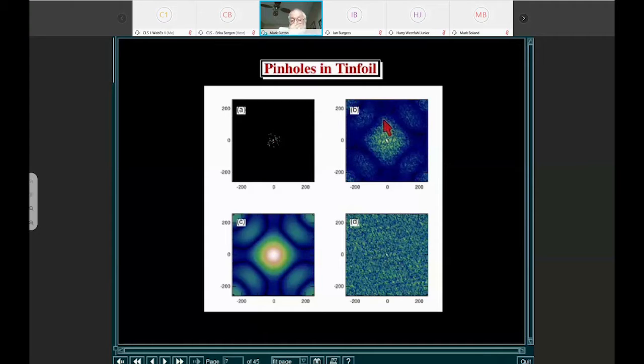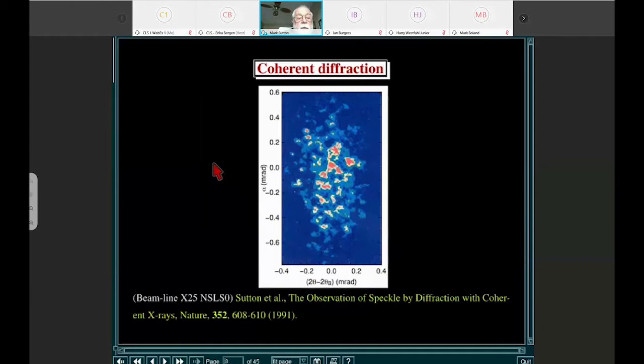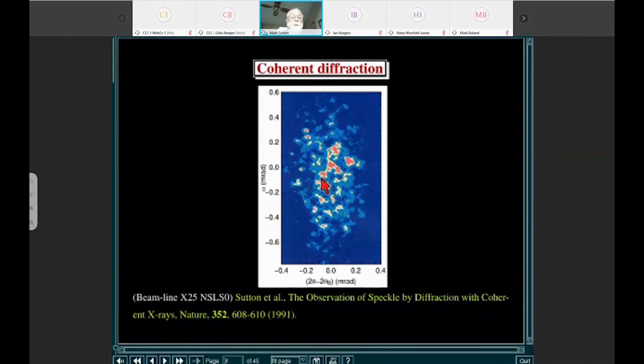And here's the start of the system. Way back in 1991, we showed that we could get a coherent beam of X-rays. And if we shone that on a single crystal of copper-3 gold that had many, many anti-phase domain walls, basically some of the bright peaks were spread out into diffuse scattering. And now again, we see our two length scale diffraction patterns.